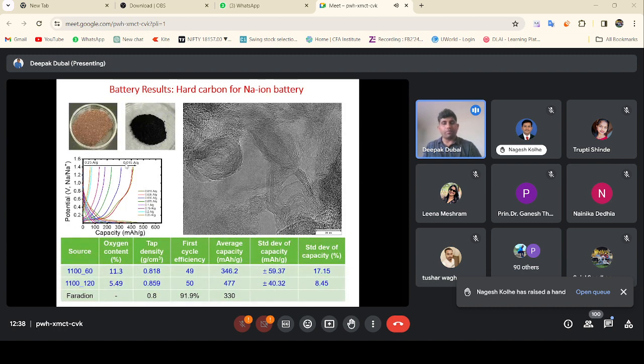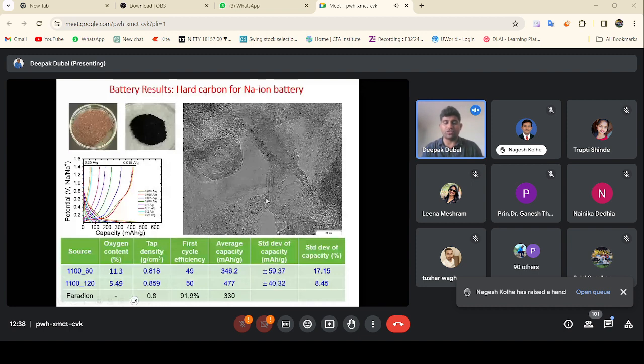With the microwave, because it is localized heating at a very low temperature, somewhere around 1100 degrees, you can see in this transmission electron micrograph all these graphitic structures. So we are forming highly crystalline, graphitic carbon materials at a very low temperature. As I said, if we want to synthesize graphite, we need at least 2800 degrees Celsius. But with the microwave, with just 1100 degrees Celsius, we could develop this kind of microstructure, and the feedstock is simply a winery waste.